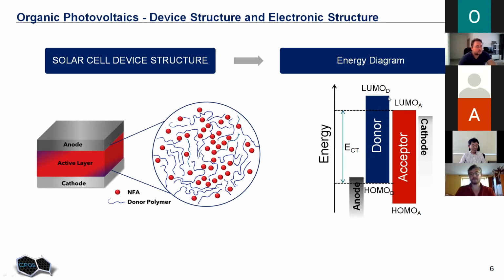Therefore, we need to create some quantum discontinuity at the interface between two materials, organic semiconductors. So we have LUMO-LUMO offset and HOMO-HOMO offset. This shift of energy alignment between two materials creates conditions when this photo-generated exciton reaches the interface between donor and acceptor inside this bulk heterojunction layer. They can be split into free electron and hole and then contribute to electric current. So this is obviously the main component of organic solar cell.